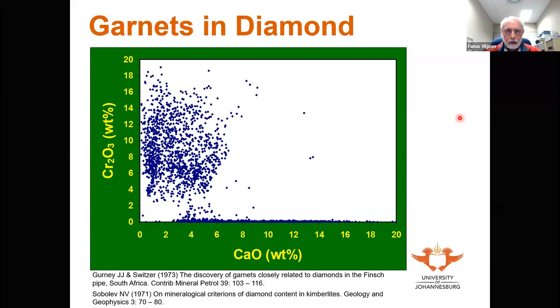If we look at that classification in more detail by interrogating the chemistry of garnets occurring as inclusions in diamonds, in terms of their chrome content as well as their calcium content, you can see that we essentially have two fields on this diagram, one of which represents peridotitic garnets occurring as inclusions in diamonds. And the vast majority of those peridotitic garnets occurring as inclusions in diamonds plot to the left of what is known as the Gurney line.